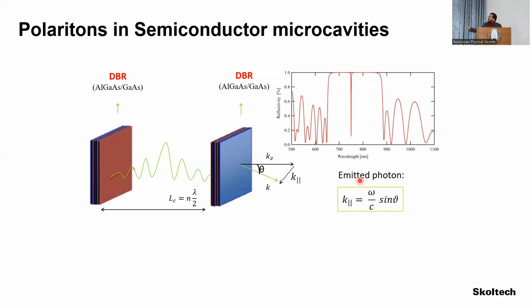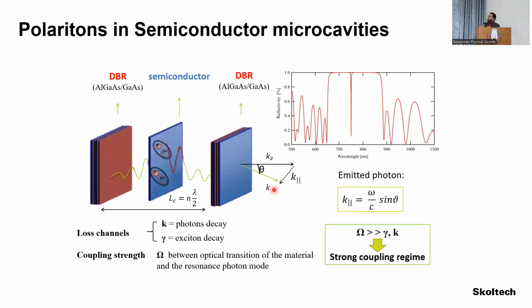The photons that are coming out of the structure can be coming out at normal incidence, but also at an angle. So the photon can have an in-plane momentum inside the cavity. And now what we do, we position a semiconductor resonant to the antinode of the field, and the semiconductor has an optical transition which is resonant to the cavity, and therefore now I will have an interaction strength of Omega, which when it exceeds the loss mechanisms in the system, such as the photon decay or the exciton non-radiative recombination channels, then we enter the strong coupling regime.